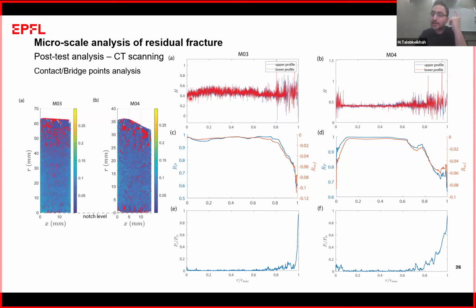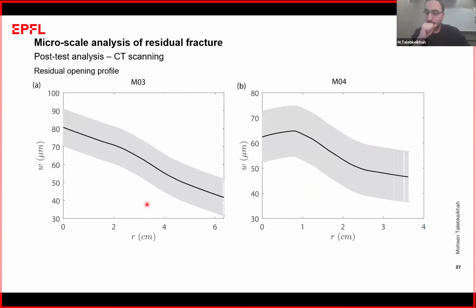And we also calculated the Hurst exponent for each CT scan along the fracture propagation direction, and we see a huge perturbation when we reach this process zone. We could see this for both experiments. So the main reason that we have a residual opening after the experiment is the presence of these contact and also unfractured or bridge points. In the end, I could also profile the residual opening from the inlet to the tip of the fracture.